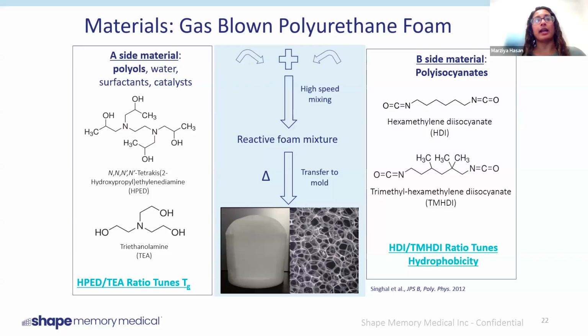We typically have a side A resin that consists of polyols. We have tetrafunctional and trifunctional polyols, which the resin will also include things like blowing agents that are water, surfactants for cell stability, and catalysts to expedite the reaction. Once we mix side A with side B, which tends to typically be our isocyanate resin, so we have some linear diisocyanates that we end up using. We'll combine these two resins using some high-speed mixing, and the resulting foam mixture will get transferred into a mold, which will then give us the foam that we currently use in our devices.